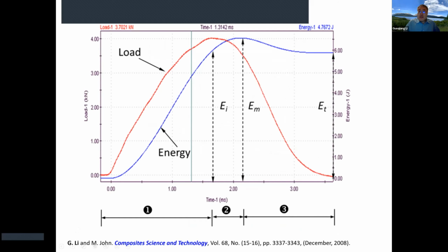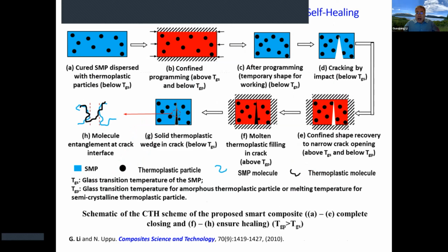If you use this synthetic foam as a core material for sandwich structures and do a low velocity impact test, you can see that the load and energy history with time are exactly the same as for conventional synthetic foam. Of course, the difference is that this type of damage by low velocity impact will be able to self-heal due to the shape memory effect. Now I give you a brief introduction of how the idea works. You start with a synthetic foam using the shape memory polymer as a matrix, and then you distribute some thermoplastic particles or fibers as a heating agent.